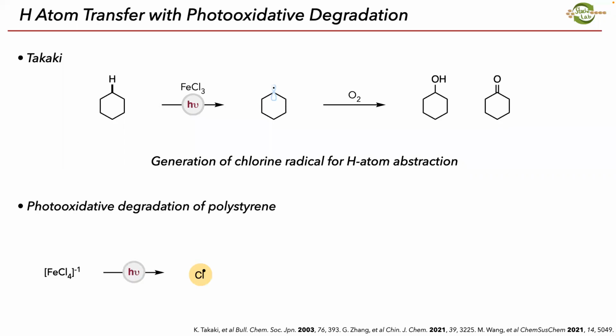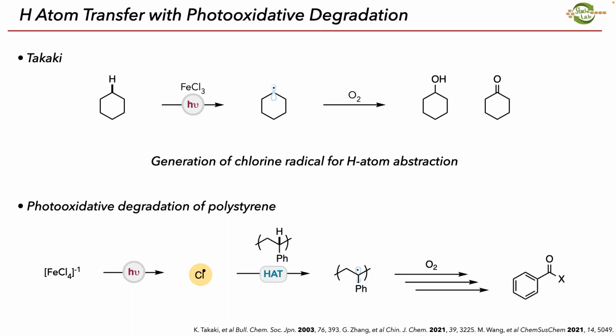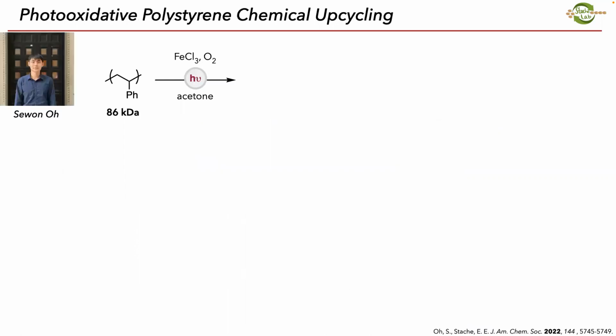And so what we proposed, or what we imagined, is that we could take iron trichloride, generate chlorine radical, which will abstract a hydrogen atom very efficiently, generate these radicals on the backbone of polystyrene, and then in the presence of oxygen, it will react with oxygen and then start to oxidatively cleave into these small molecule byproducts.